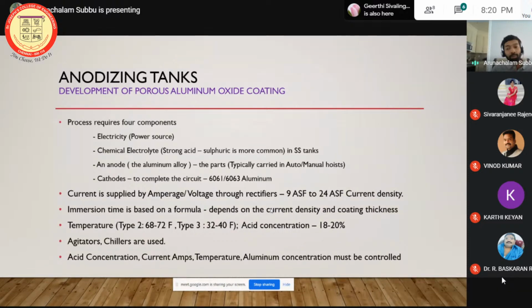And yeah, the current has to be supplied through rectifiers. It will be supplied either through amperage or through voltage. And the current density is really important for the anodic coating. How will you calculate how much current you have to supply to get a certain thickness? That depends on a formula involving the current density and the coating thickness. The current density varies from 9 amps per square foot to 24 amps per square foot, and the electric current that you supply depends on the square footage of the part. So if it's a very big part, you'll be supplying a lot of electric current. That's a really important thing to know.